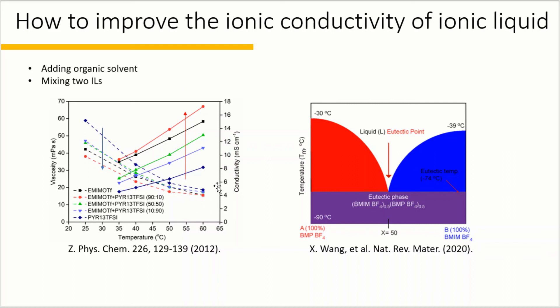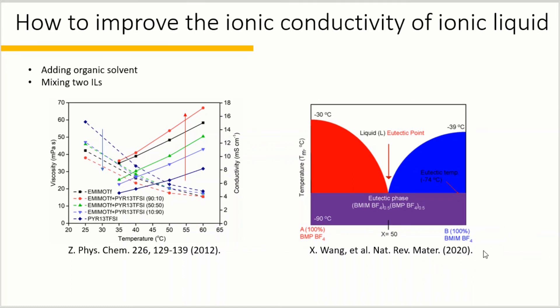Here, the viscosity decreases and ionic conductivity increases in a binary mixture of EMIM-OTF with PYR13-TFSI. Binary mixtures of ionic liquids have also been investigated in order to shift the crystallization to low temperatures. Here is a phase diagram proposed based on the melting temperatures of various mixtures.